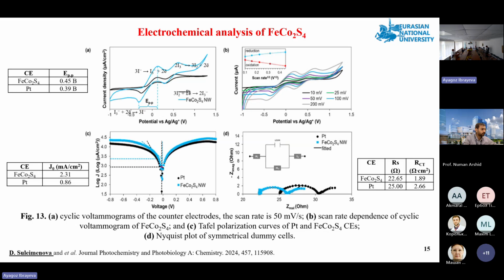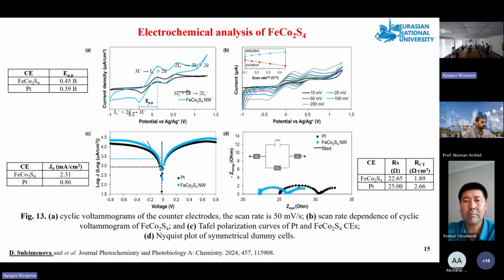The cyclic voltammetry results show that ferrum cobalt 2 S4 has a higher cathodic current density than platinum, which means better catalytic activity. However, the gap between its peak separation is slightly larger, which suggests a somewhat slower reaction rate. This can be explained by its structure, as it contains many defects and exposed surface areas that provide more active sites. CV tests at different scan rates show stable behavior and good ion diffusion.